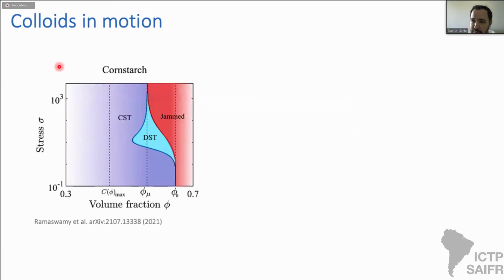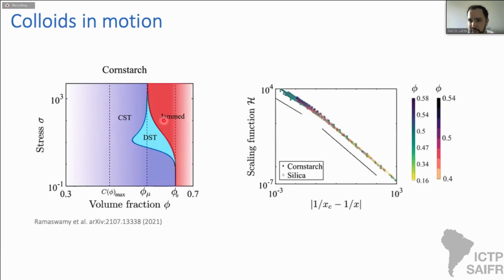So the phase diagram in terms of stress and volume fraction has a region of continuous shear thickening, a region of discontinuous shear thickening where the viscosity jumps, and a jammed region. I've recently been part of a team that proposed a phenomenological scaling theory to explain extensive experimental data on solutions of cornstarch in glycerol. Now, the challenging aspect here is that it can happen even far away from the jamming critical point. So it's surprising that one is able to produce such good scaling collapse of data like the ones I'm showing here. I'll not discuss the details